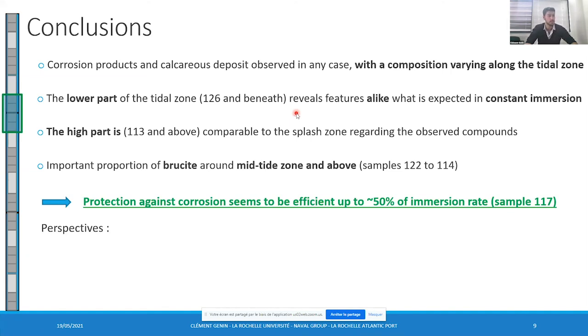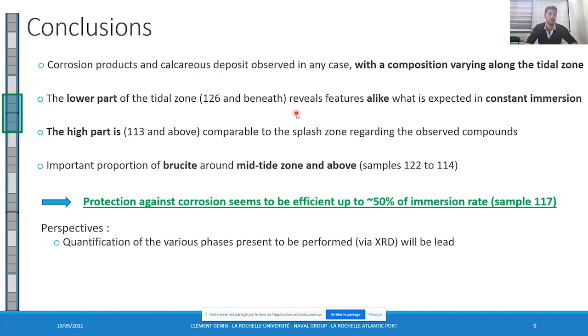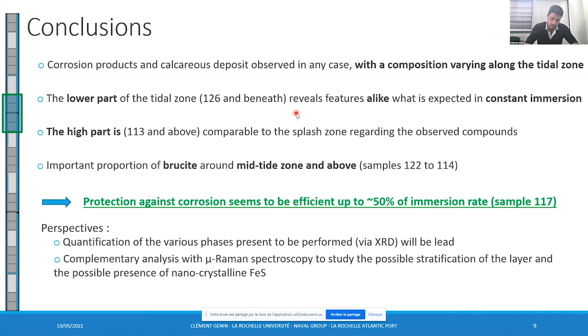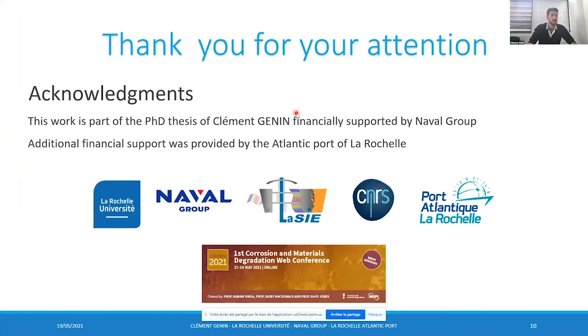This hypothesis has to be confirmed with further studies, such as the quantification of the phases present here via XRD analysis. Micro-Raman spectroscopy should be led to understand better the stratification and the possible presence of nanocrystalline phases, and then to evaluate the corrosion rate in this zone. Thickness loss measurement should be performed too. Thank you for your attention and for permitting me to present my work here for the first time.